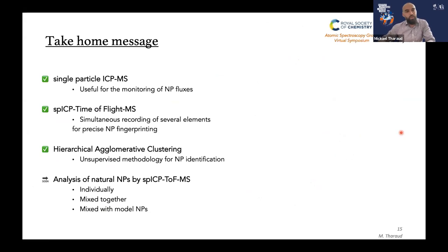And to finish, for the take-home message, we can say, as Eduardo said, that single particle ICP-MS is very useful for single particle events, and it's useful for the monitoring of nanoparticle fluxes. However, by using a monoelemental approach, we do not have any information about the nanoparticle composition. So that's why single particle time-of-flight mass spectrometry is more adapted in order to simultaneously monitor different elements at the same time and to determine the nanoparticle fingerprint.